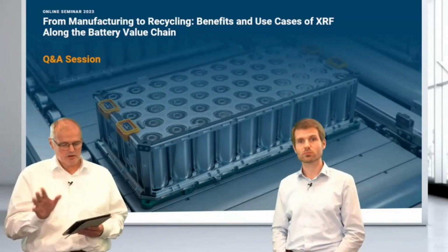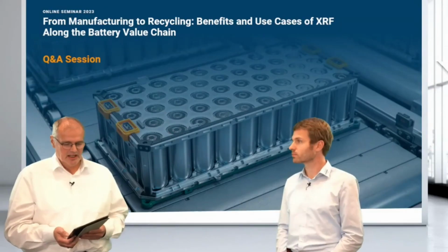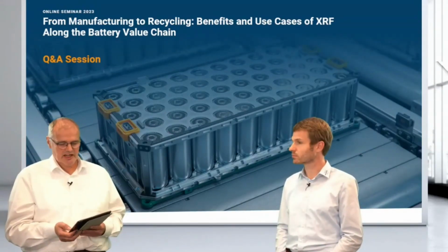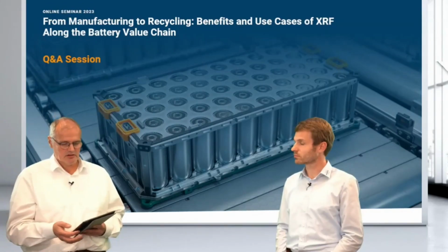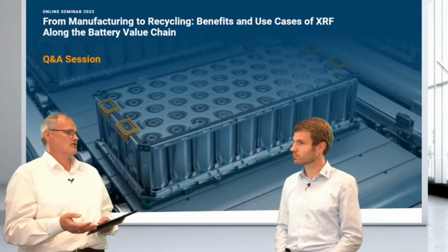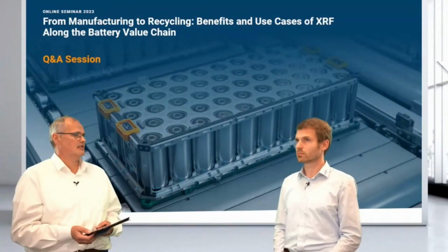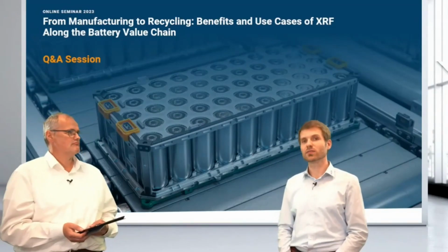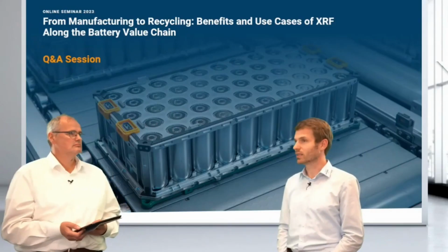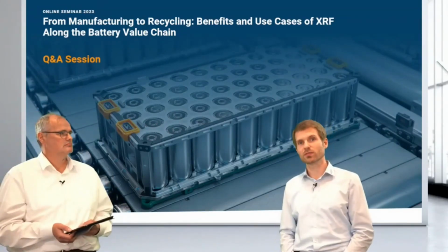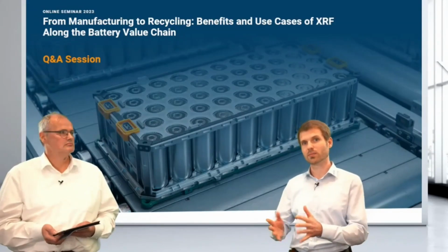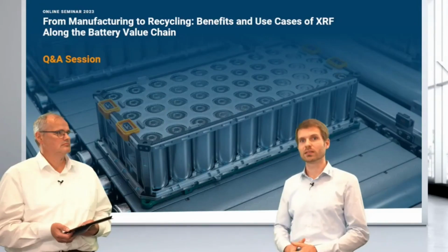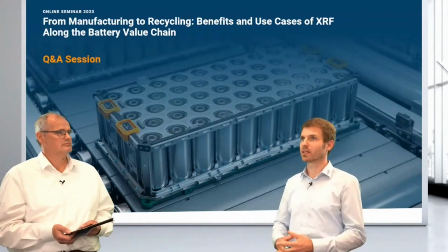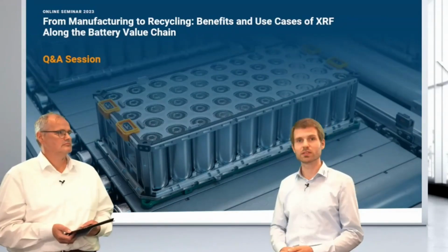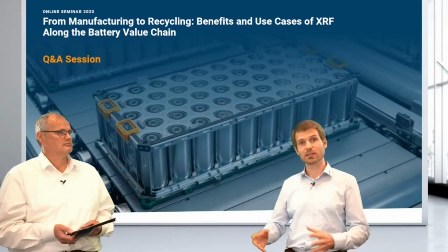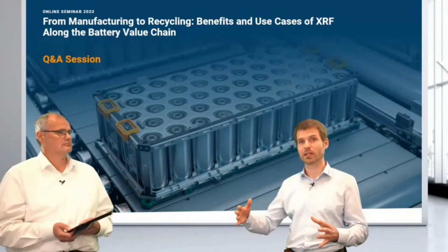One of the last questions we are answering today concerns measurement accuracy: which deviations can be seen concerning the grain size particle effect? So the grain size has an effect. Let's put it this way. Normally, a sweet spot for XRF, where you get the best signal and data, is on the order of a few tens of microns, so 40, 50, 60 microns. That's ideal. But you can also get very robust results for much larger particles.